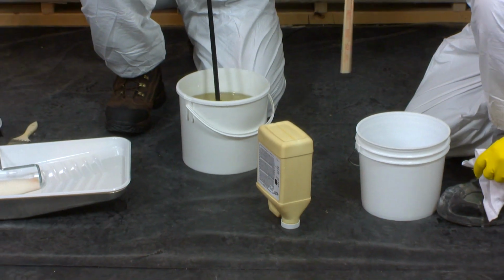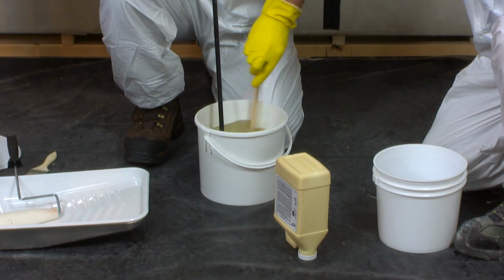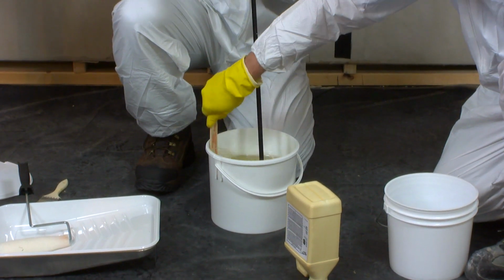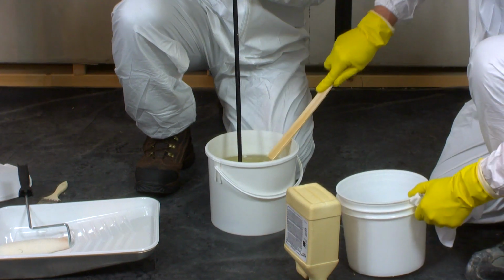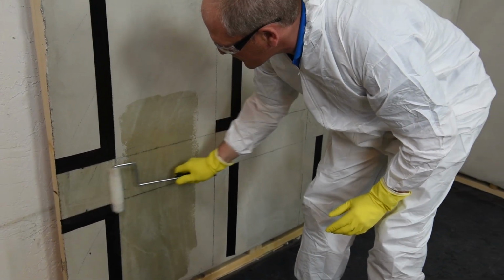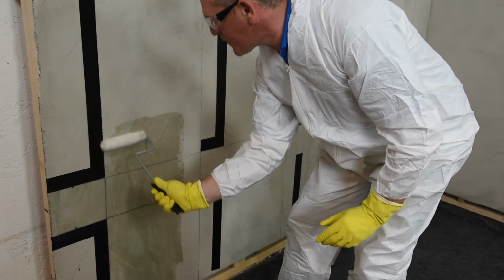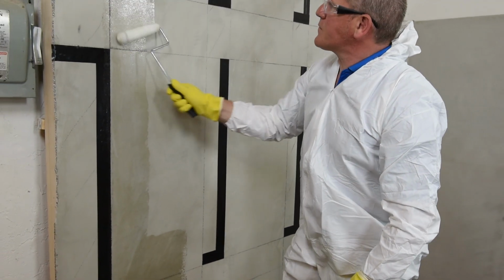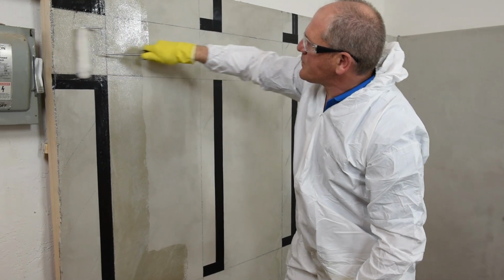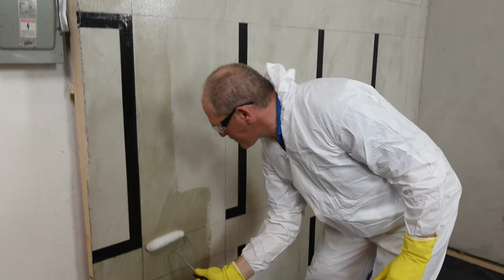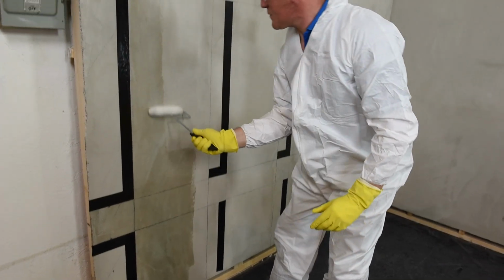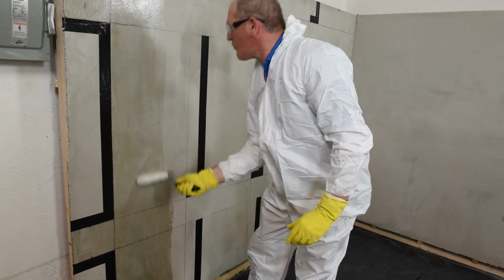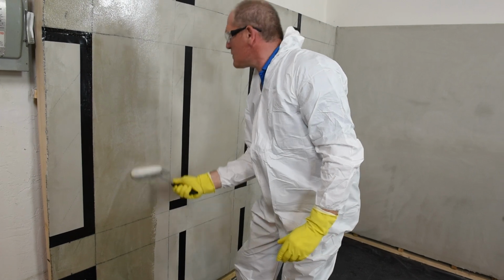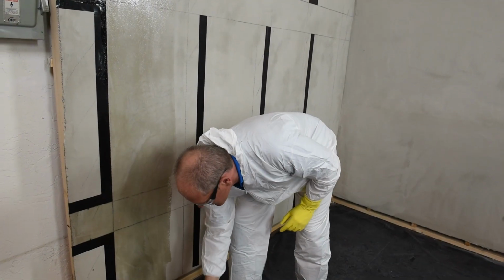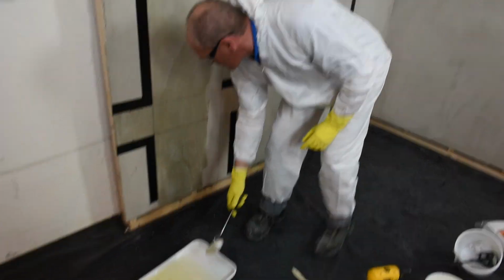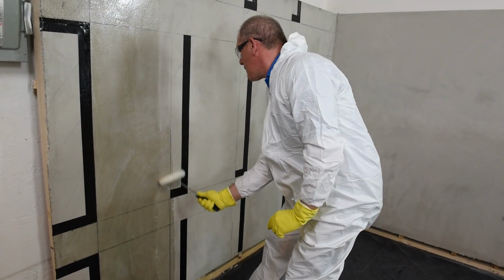MapeWrap Primer 1 is used in order to consolidate and prime the substrate, which optimizes bonding performance for the other components of the MapeWrap composite system. MapeWrap Primer 1 is installed with a 3/8 inch or 10 mm nap roller at a rate of 150 to 190 square feet per US gallon, or 3.67 to 4.65 square meters per liter. Very porous substrates may require a second coat after the first coat has been completely absorbed. Once prepared, MapeWrap Primer 1 has a working time of 90 minutes.